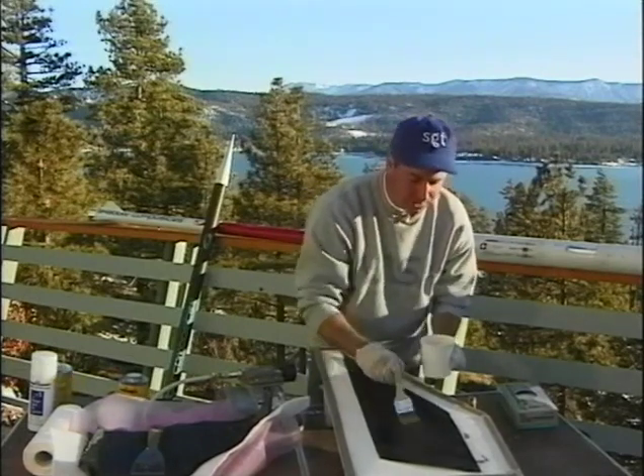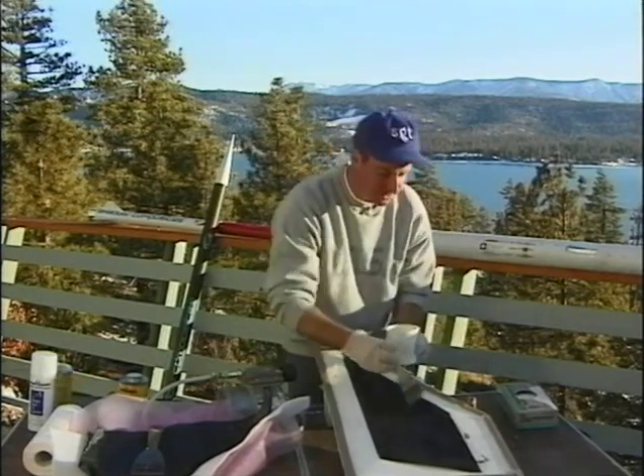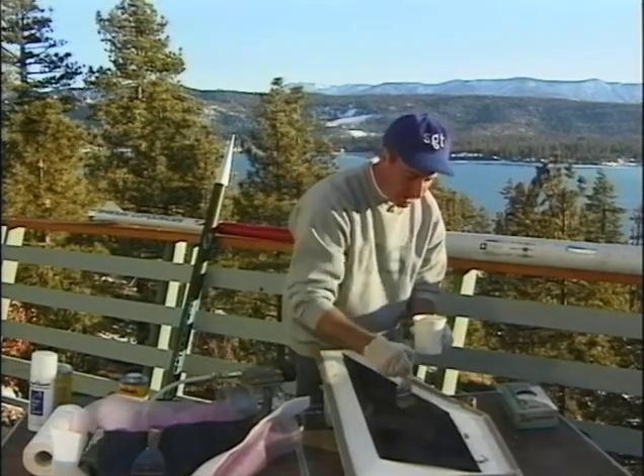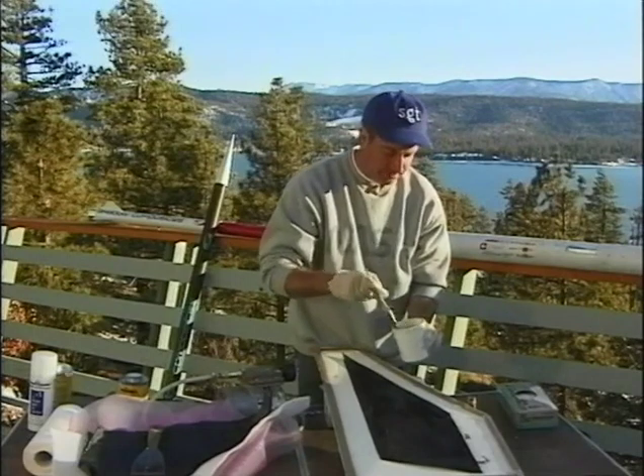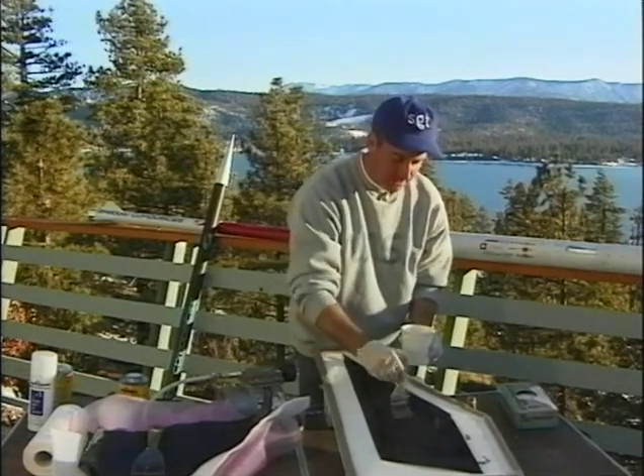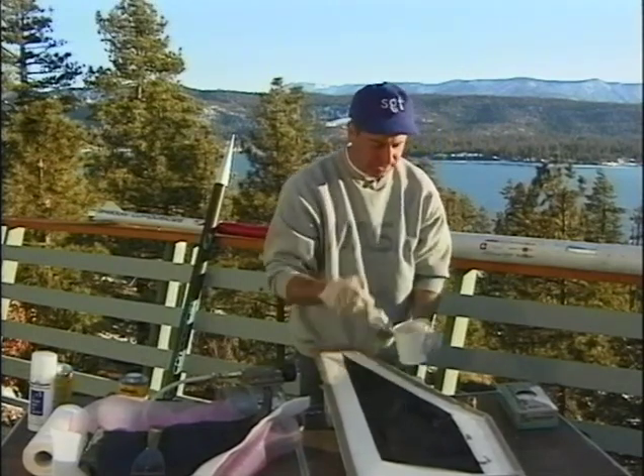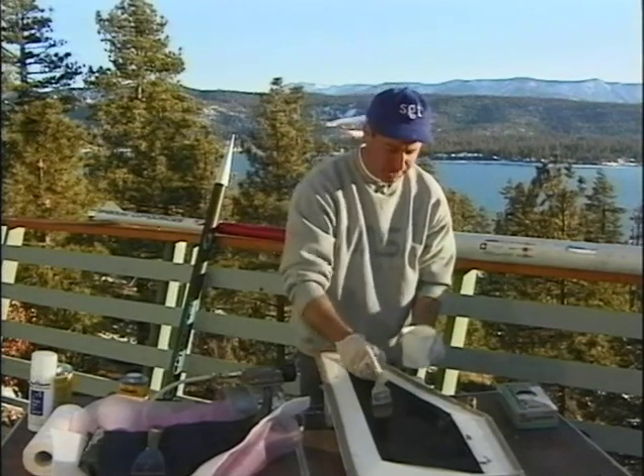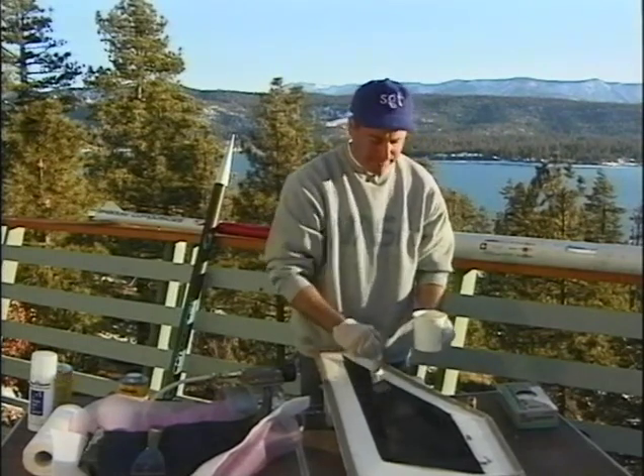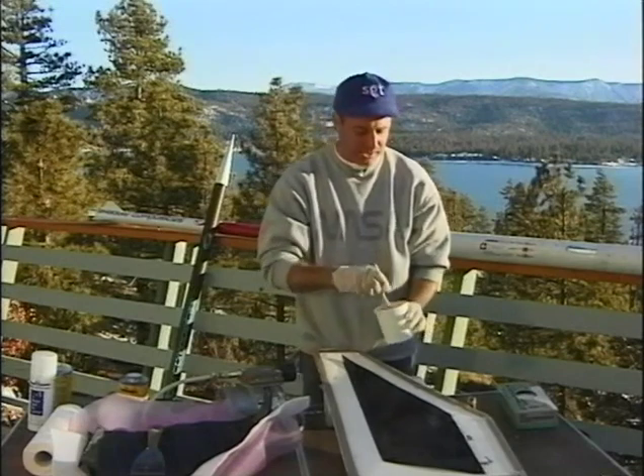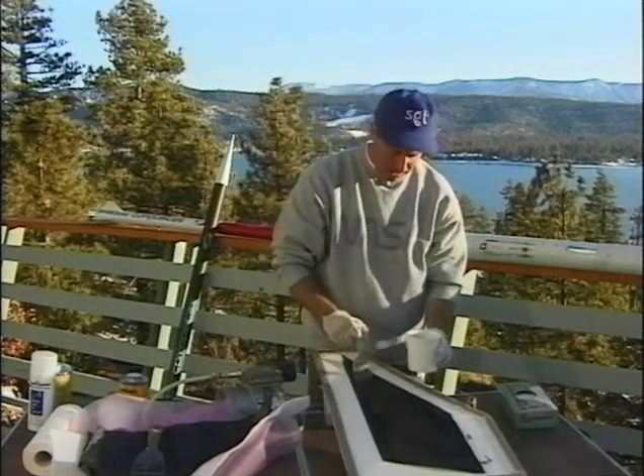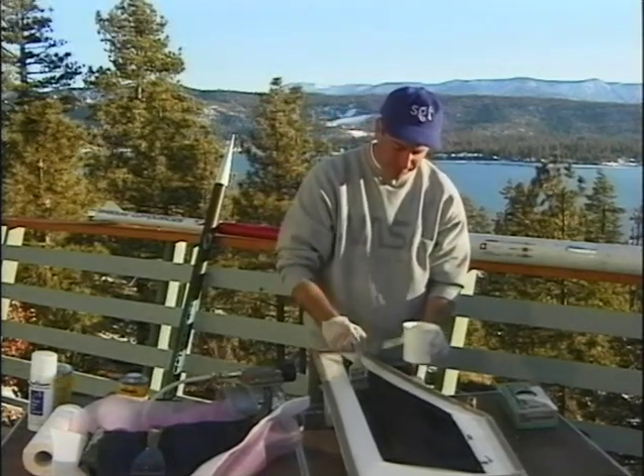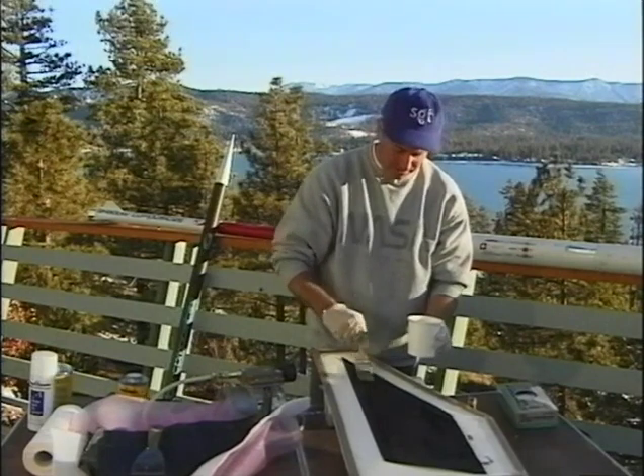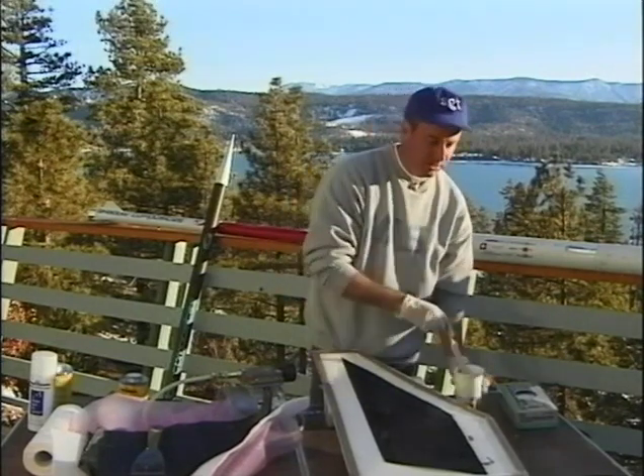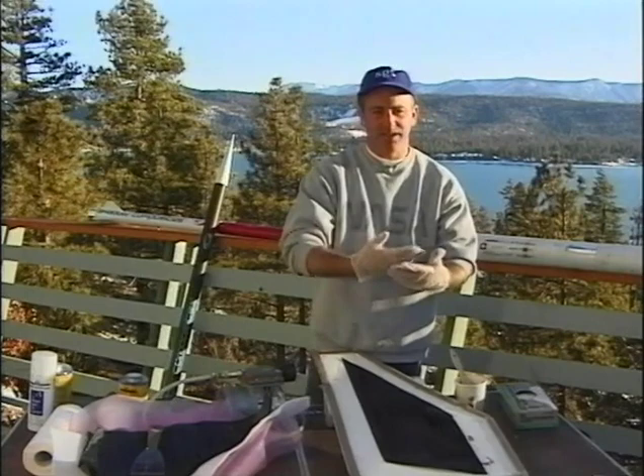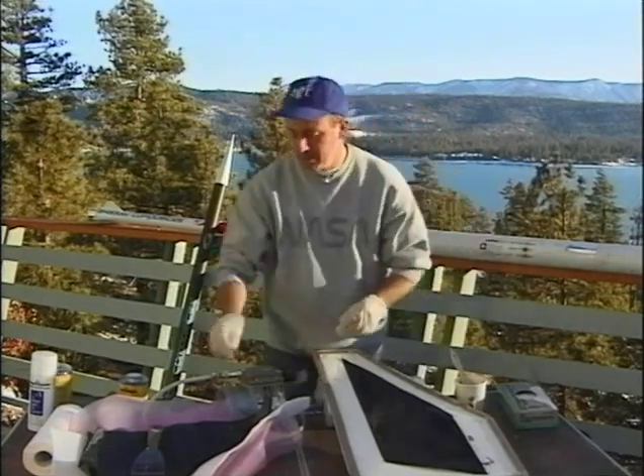You can also use a caul plate like that on flat structures like the first one that we did, to help smooth it out. What I wouldn't do is, I talked a little bit about people weighting laminates between two layers of glass. That's very dangerous, actually. If you want to do that, you can get away with it, but keep a very good release on both layers of glass, or when you go to pull that second layer of glass off of the laminate, it's going to shatter. So just be careful.